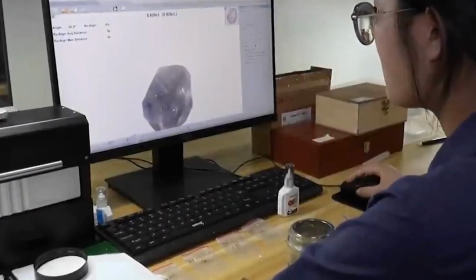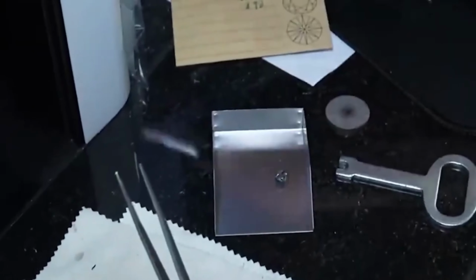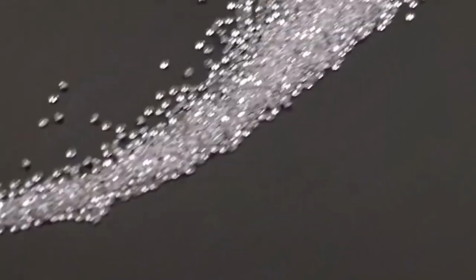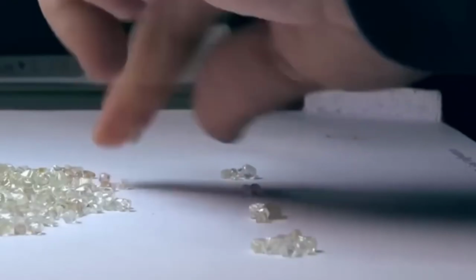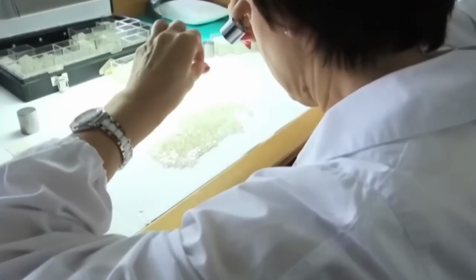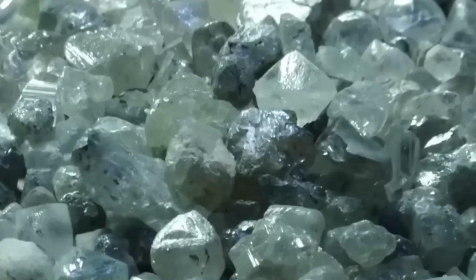After annealing, the diamonds move to the planning stage. Rough diamonds, even lab-grown ones, rarely have perfect shapes ideal for jewelry. They often appear jagged, cloudy, or uneven. Diamond planners use lasers, 3D scanners, and specialized imaging systems to map every internal feature. They identify inclusions, cracks, growth lines, and the best way to cut the rough stone for maximum clarity and carat yield. This planning process determines whether a rough diamond becomes 2 small stones, 1 large stone, or a specific shape like round, brilliant, princess, oval, or cushion. Planning is both an art and a science. A great planner might recover 40% more usable material from the same rough compared to an inexperienced cutter.